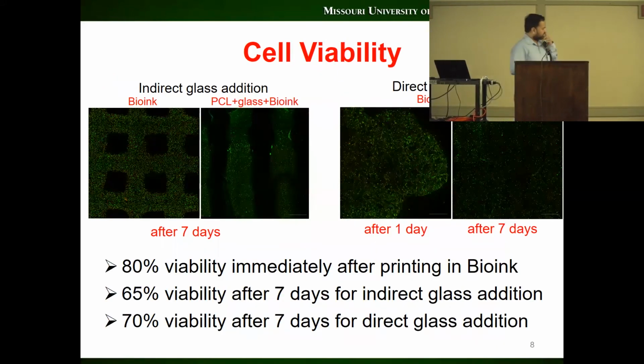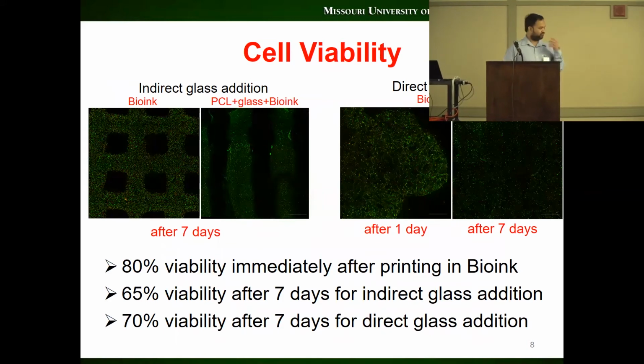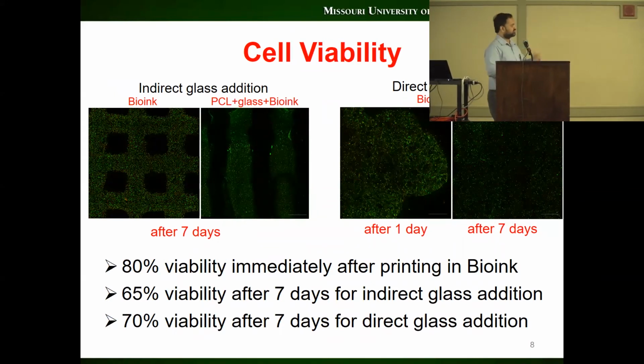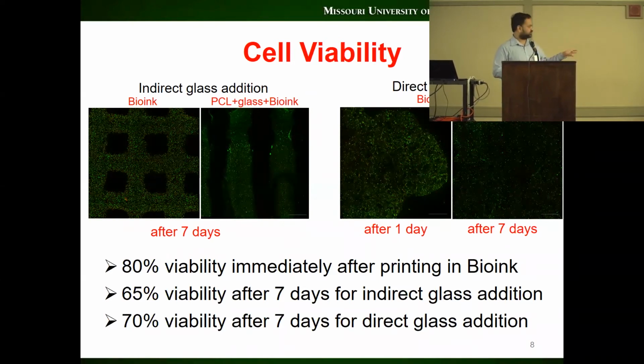We have come to a point where we found out that the alginate and gelatin composition works best, and then we incubated the scaffolds with cells in them for 7 days or 14 days. I think it's kind of difficult to see in the picture, but we see good viability. Immediately after printing, we get more than 80% viable stem cells, and then after 7 days and 2 weeks, we get around 70% viability.